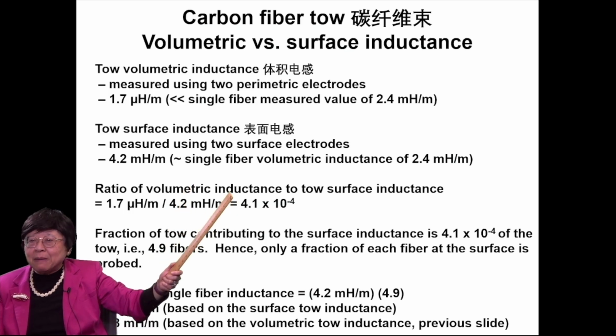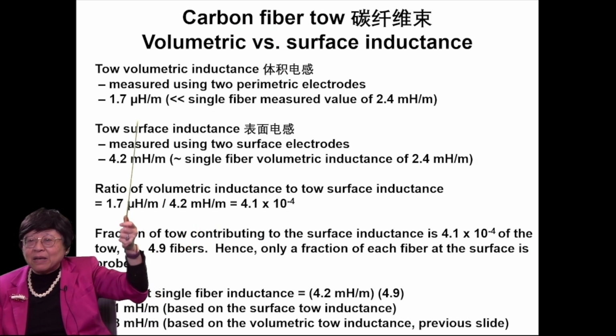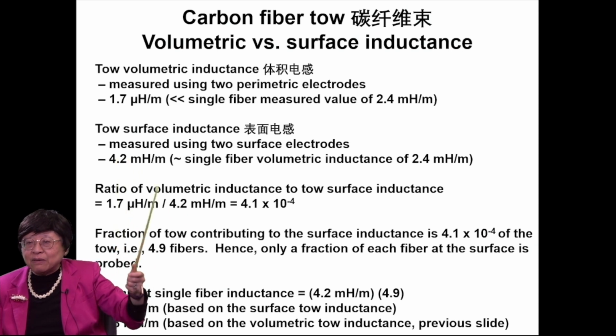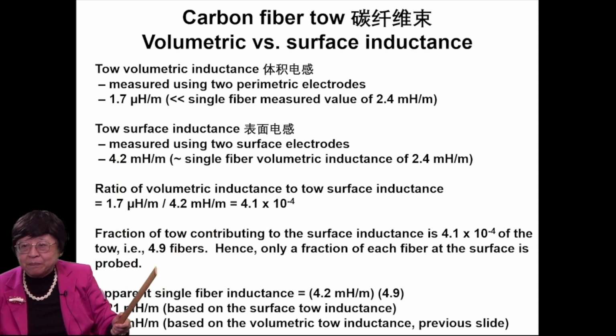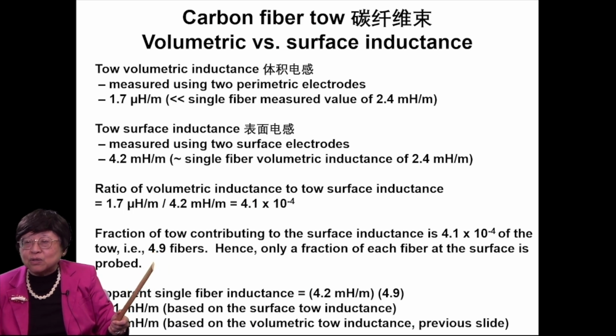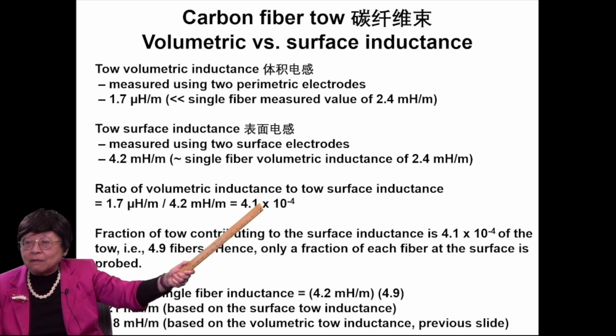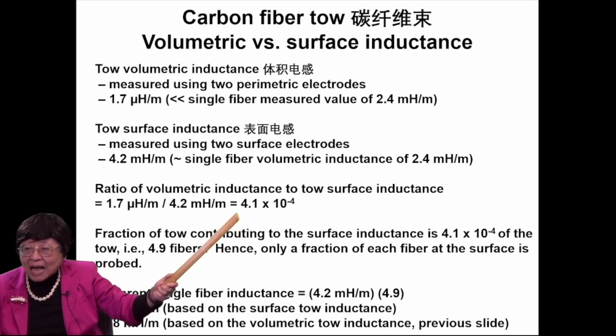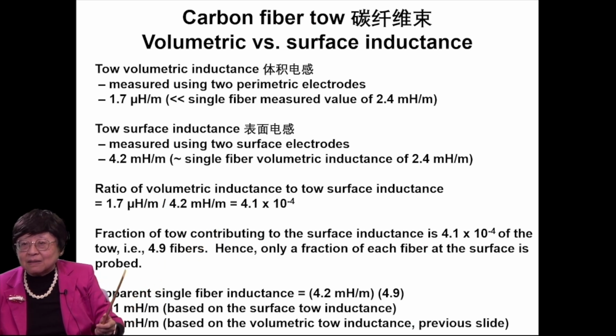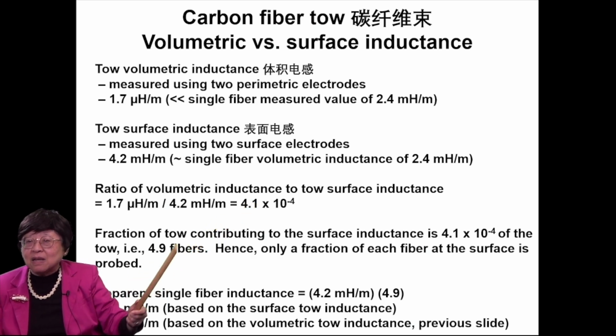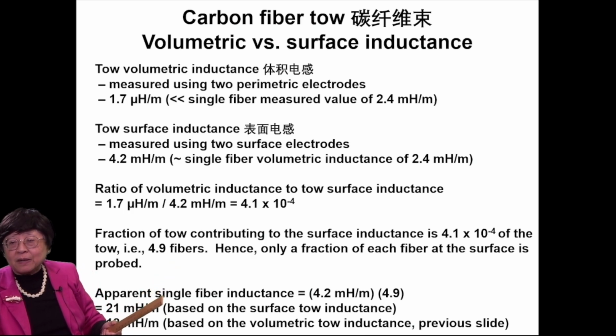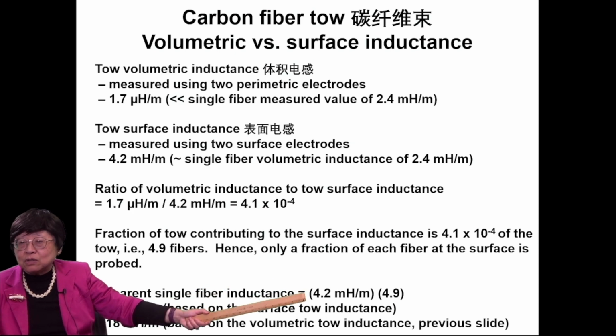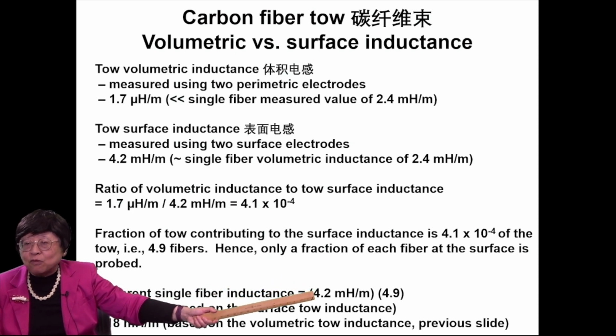The ratio of the volumetric inductance to the surface inductance of the tow is 1.7 microhenry per meter divided by 4.2 millihenry per meter. That's 4 times 10 to the minus 4. So the fraction of the tow contributing to the surface inductance is this fraction of the tow. Okay, so this times 12,000, that means 4.9 fibers only. Only a fraction of each fiber at the surface is probed. The apparent single fiber inductance is 4.2 millihenry per meter times 4.9.